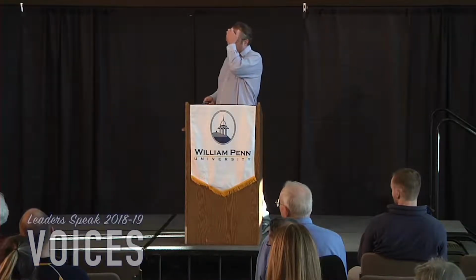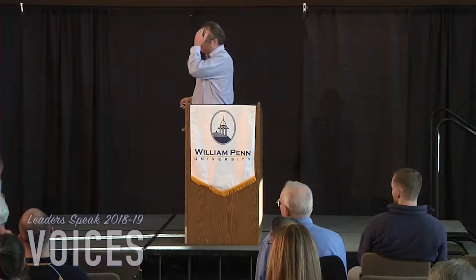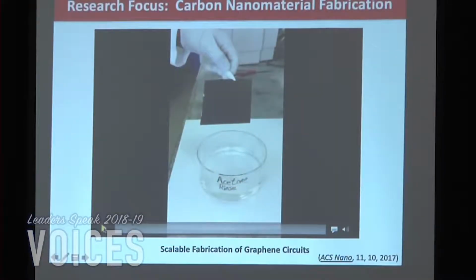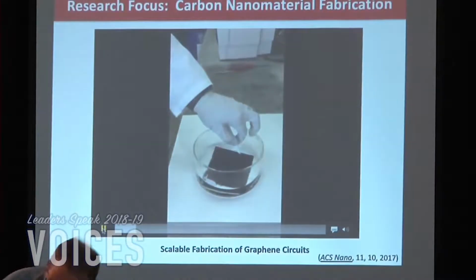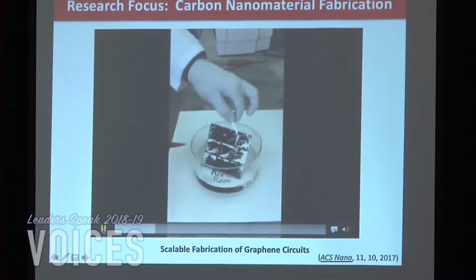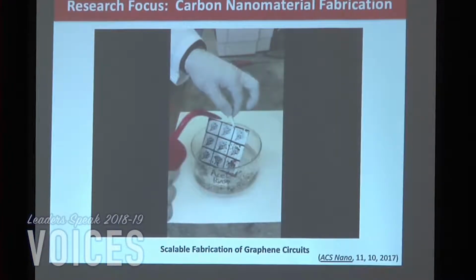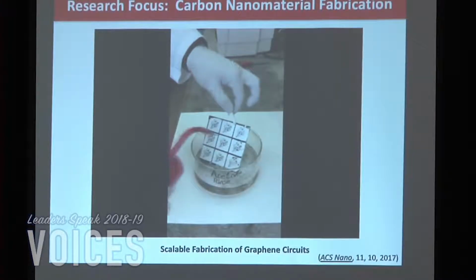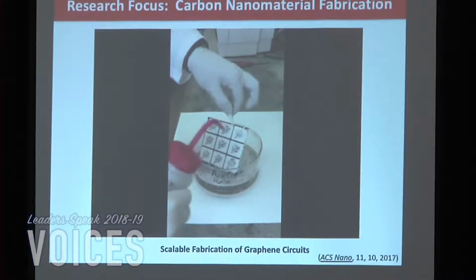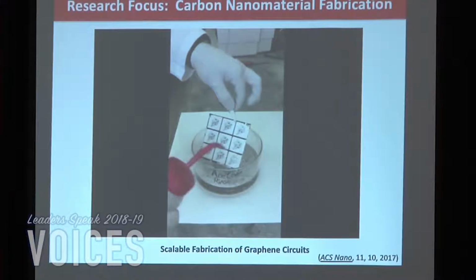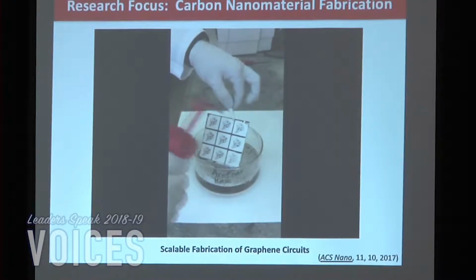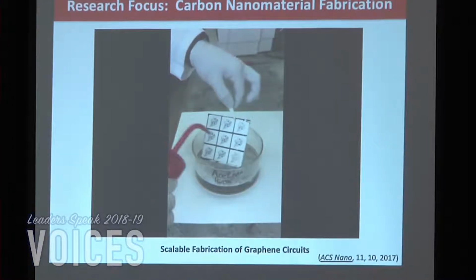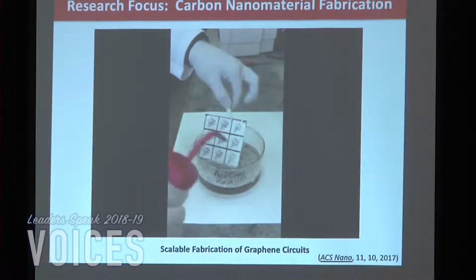So here's a little video. Yeah, we're going to get this started for you. So this is a video that's showing we've printed a polymer underneath, and then in this case we've spin-coated a layer of graphene flakes on top of this, and that's the black that you see on top of this white polymer, and that's a bath of acetone, and we're mixing it around. And it might be a little hard to see, but that does not say William Penn, that says ISU. It's a cyclone, the cardinal for ISU, that's Cy. So it's just to show you how easy it could potentially be to make these types of circuits.